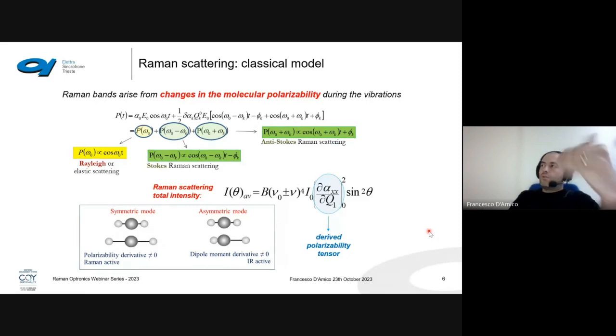In the classical model, to have the quantitative difference between infrared and Raman, Raman bands arise from changes in molecular polarizability, differently from infrared, where variations are due to dipole moment variations. And this has an important consequence in the efficiency. Specifically, the molecular polarizability determines the Raman cross-section. A symmetric mode, like the stretching, has a nonzero polarizability derivative and is Raman active. Otherwise, asymmetric modes have a dipole moment derivative different from 0 and are infrared active. This difference is important because it means that the same sample may give a different vibrational spectrum in infrared and Raman.